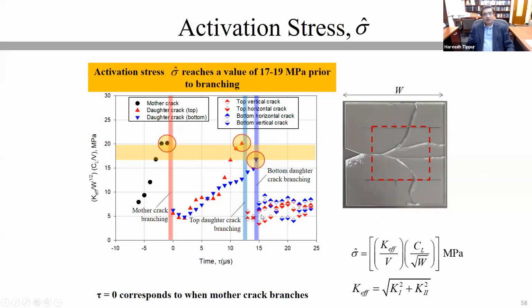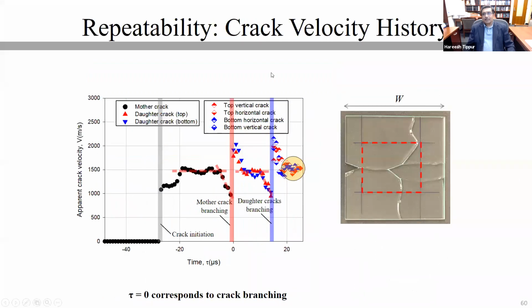So when I look at the 4 granddaughter cracks, none of these reached a high enough value of this 17 to 19 megapascals. Remember, the low value of tensile stress for this material is somewhere around 45 that is reported in the literature. So this value, this activation stress, in my opinion, is significantly lower for all these 4 granddaughter cracks, and we are not seeing any branching, by that consistent observation that we have made relative to the previous experiments. So here is one experiment.